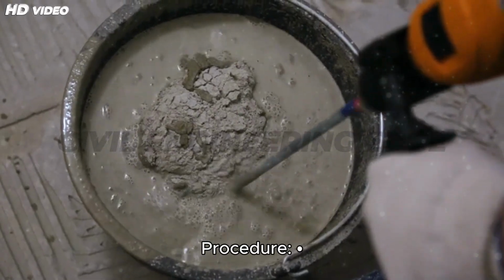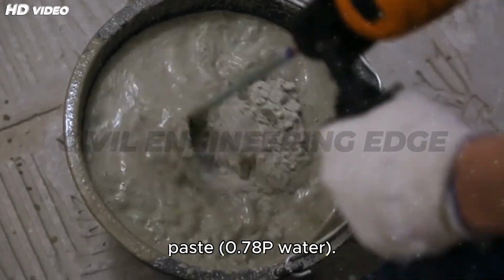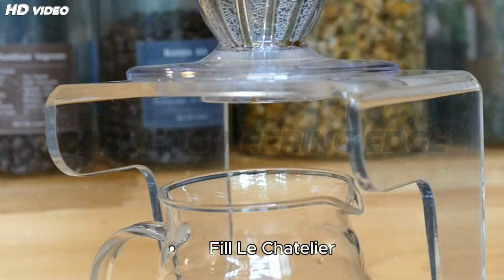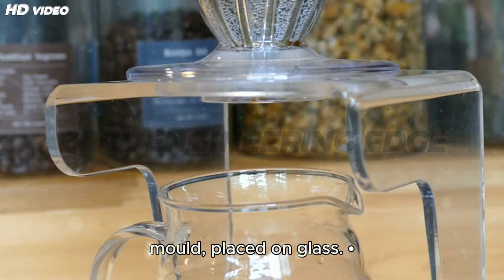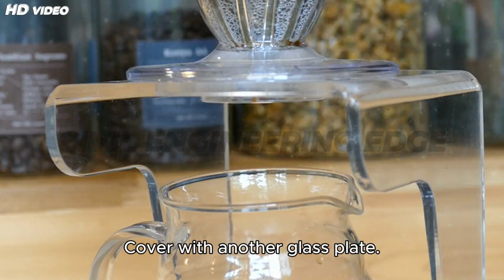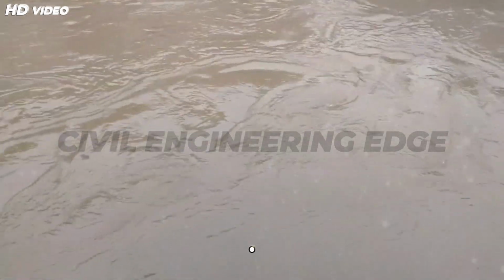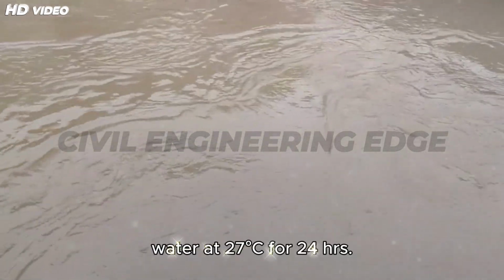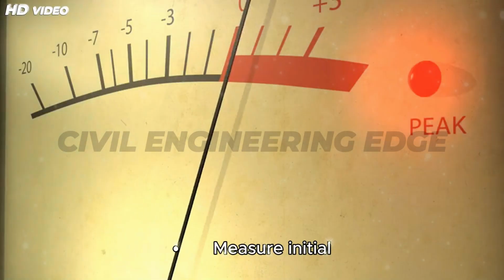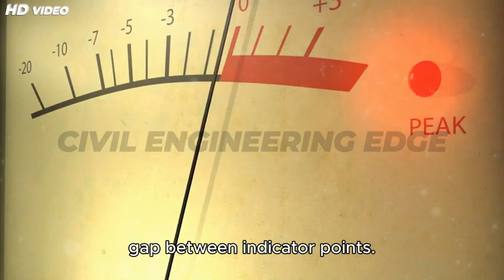Procedure: prepare a cement paste with 0.78 P water. Fill the Le Chatelier mold placed on glass. Cover with another glass plate. Submerge in water at 27 degrees Celsius for 24 hours. Measure the initial gap between indicator points.